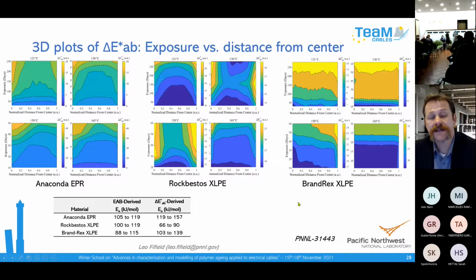Here, these are a little different plots than the first one I showed, where they showed all the temperatures on the same plot. These have a different plot for each temperature versus time of exposure. So you see that this inhomogeneous behavior also evolves with time at given temperatures. At low temperatures, it in general happens less severely than at higher temperatures. These plots, calculated using color change, show aging as a function of location through the thickness of the material over time.